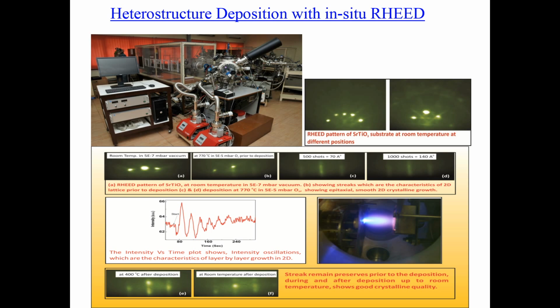You can do reflection high energy electron diffraction of this surface, and that will give you these spots because you are growing layer by layer. And if you monitor the intensity of one of these dots, then you actually see oscillations, because whenever you complete one layer, you get maximum intensity, and when you start the process of making the second layer, the intensity drops. And when again you complete a second layer, intensity is at the peak. So from these intensity oscillations, you can actually count how many layers you have put on the surface.